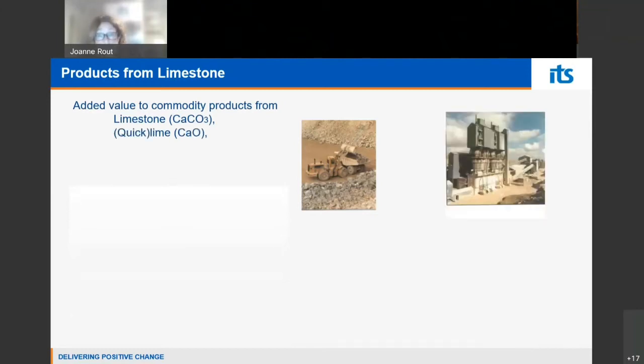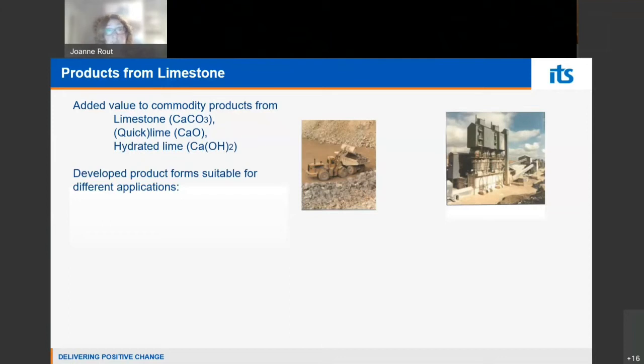We had kilns which produced the quicklime. You heat the limestone to 1200 degrees C and you form calcium oxide, and carbon dioxide is given off. Then if you add water to that, you can form hydrated lime, sometimes called slaking. Some people might remember these terms. If you add water to it, you can form milk of lime. Who can remember milk of lime from chemistry lessons, testing for carbon dioxide? So what we were doing is trying to add value to these pretty much commodity products. We were looking at different product forms for different applications to meet different specs of customers.